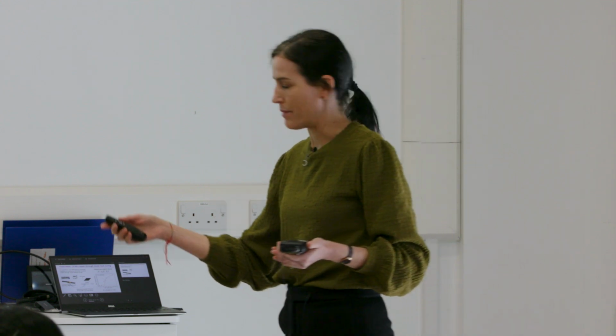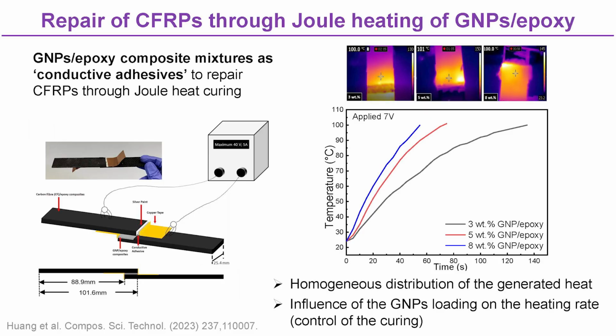We found that in this direction, the percolation threshold was around 3%, which basically means that any loading above 3% should work for this particular application. So we tried 3%, 5%, and 8% graphene, and we found that the three of them worked quite well. The electrically conductive 3D network of graphene incorporated into the matrix could successfully transform the electric current into heat in the three cases, successfully curing the adhesive, and then successfully repairing the composite.